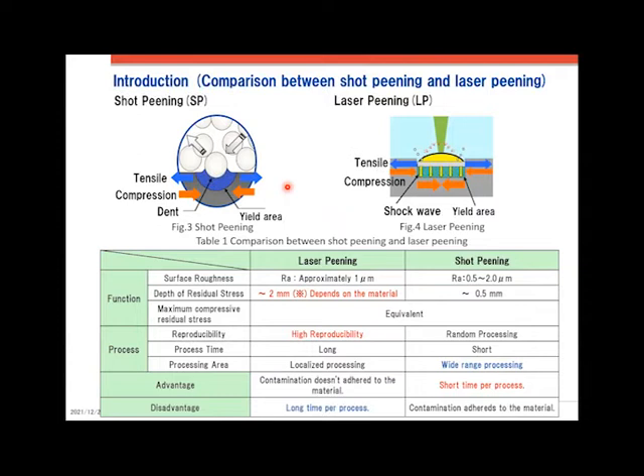So, peening is one of the methods to improve the fatigue strength. Two major methods of peening are shown here. Shot peening uses metallic or non-metallic special media, which is called shot media. The shot media is accelerated by various methods. The accelerated media impacts the processed surface, and then plastic deformation is generated at the surface. Residual stress is generated to constrain the plastic deformation layer by the surrounding base metal. Furthermore, the plastic deformation generates work hardening.